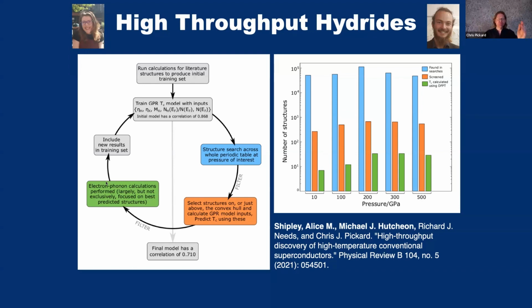And so here's just some plots. I'm not going into great detail here, but we were generating of order 100,000 different binary hydride structures at each pressure. Now that's too many structures to calculate TC for. So we used a mixture of machine learning and just fairly simple observations. If the crystal structure was an insulator, we would not calculate TC because it's going to be zero. Okay, so we can screen out a lot of the structures. If the structure is too high in energy, we won't calculate TC because you could never make it.